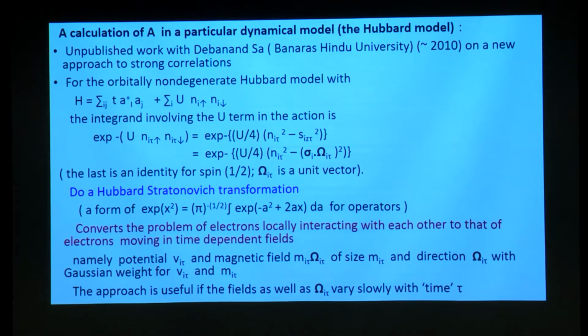Okay. The other calculation is based on a particular dynamical model for the Hubbard model, which I developed with Debanand Sa long back. This is a model for the orbitally non-degenerate Hubbard model. That is, you have electrons on the lattice sitting at lattice sites i and j. At each site, let us say the energy is 0, and this is the energy due to hopping. And at a particular site, if I have one electron with up spin and another electron with down spin, they repel each other with an energy U. I ignore everything else. It's a highly oversimplified picture.